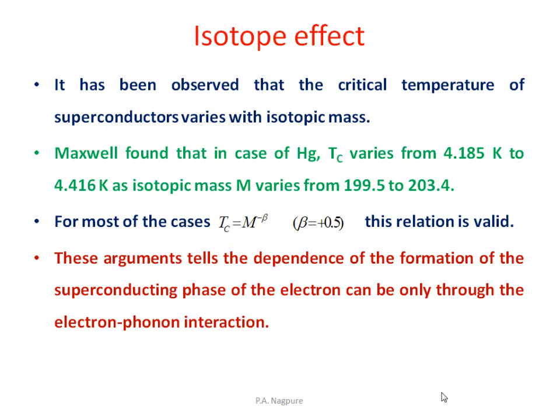Isotope effect in superconductors. It has been observed that the critical temperature of superconductors varies with their isotopic mass. Maxwell found that in the case of mercury, the critical temperature varies from 4.185 Kelvin to 4.416 Kelvin, as the isotopic mass M varies from 199.5 to 203.4. For most of the cases, the critical temperature Tc is proportional to the isotopic mass M raised to the power minus beta, where beta is a constant equal to 0.5. This relation is valid.